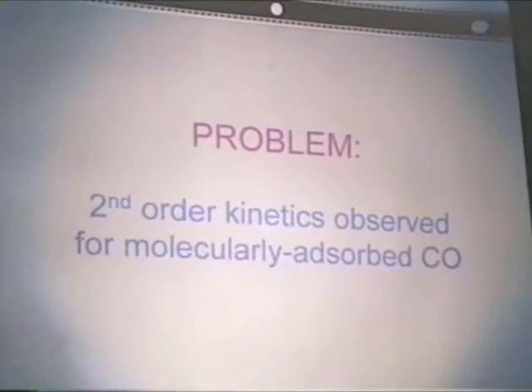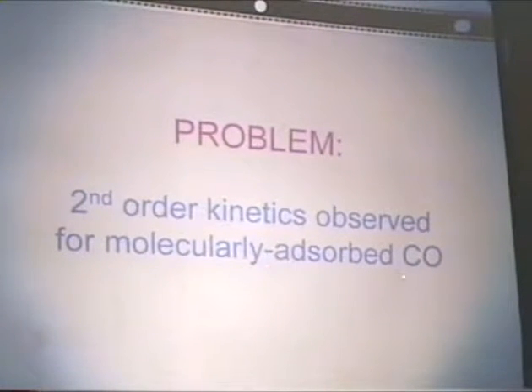So, hopefully everyone can see the problem we have. Second order kinetics for molecularly adsorbed CO, when intuitively you would expect a molecularly adsorbed CO to have first order kinetics.